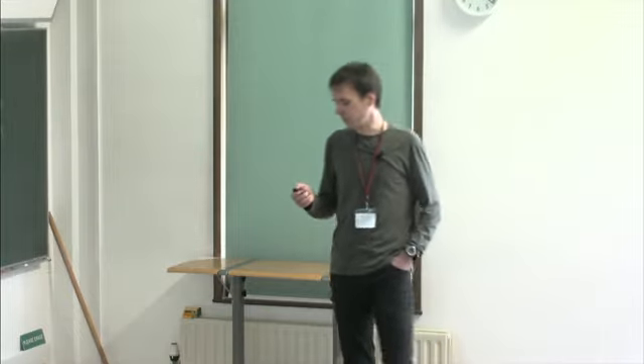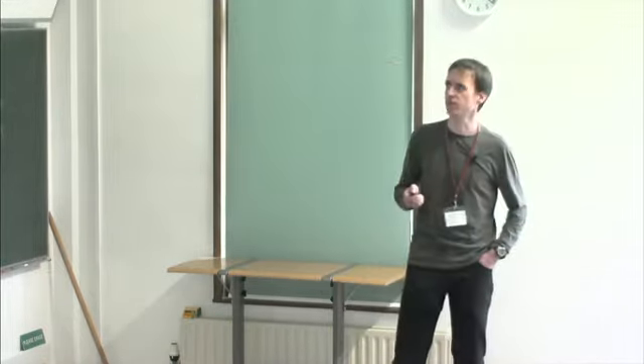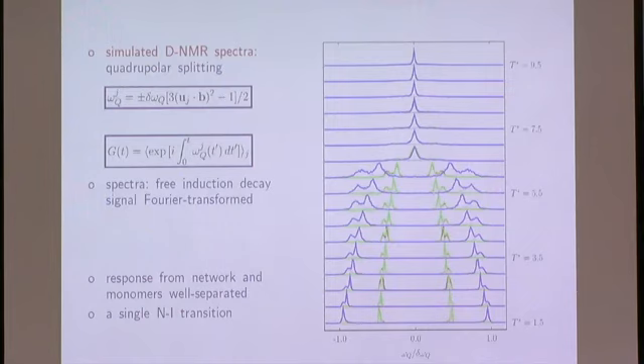Okay. Now, going to some selected experimental observables. One of the possibilities is to put your sample in an NMR spectrometer and look at the spectra to have an idea about the orientational ordering. So what you can do is deuterate your particles, and then you have deuteron nuclei with a non-zero nuclear quadrupolar moment. These nuclei feel the gradient of the carbon-deuteron bond, and it turns out that this results in a splitting of Zeeman levels once the system is placed into an NMR spectrometer. And this splitting, this perturbation, depends on the relative orientation of the molecular long axis and the NMR spectrometer field.